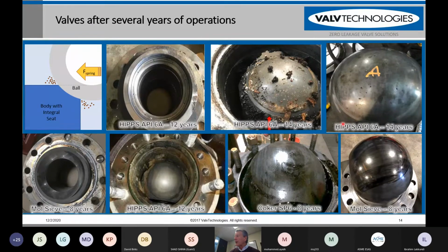Although there's slight discoloration on this valve, it's another 6A valve. It was in service for 14 years and has no leakage at all. Again, more seats. This is 8 years in mol sieve service. The seat has tungsten carbide coating on it, which makes it impervious to the weld slag, the weld beads. Here's a ball inside the valve when we first took the closure off. Again, another valve. This one was in coker service in a refinery, very high temperature, for 8 years with no consequences at all. This is one that was in service up in Canada for 8 years, and no problems with it at all.